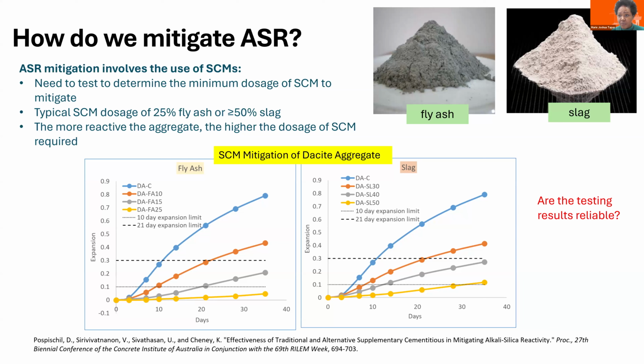The plot you see is sample accelerated mortar bar test expansion data. It tests up to 21 days. You can see that with increasing levels of SCM in the system, you get a decrease in expansion. That equates to mitigation, which means SCMs are working well. You can also see very clearly that not all SCMs are the same in mitigation. Slag, for example, would require more than fly ash, which is actually good for our low carbon concrete initiative in any case. But the bottom line is not all SCMs are the same. Okay, now the next question perhaps is, how are we sure that the testing results are reliable?